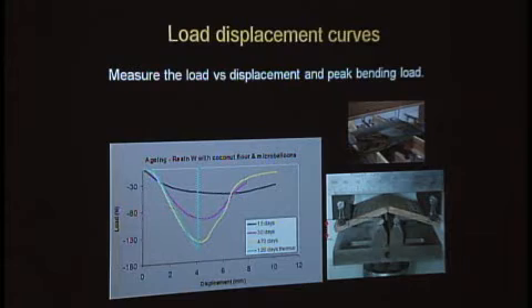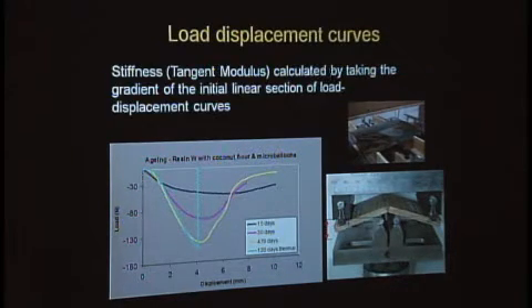This is looking at the resin W that was mentioned earlier this morning by Britta, which is a UK PVA with a mixture of coconut resin, coconut flour and microballoons, looking at it at different thermal and natural aging periods. This measurement here is negative because we're measuring compression. This is the displacement, and this corresponds to this displacement here.